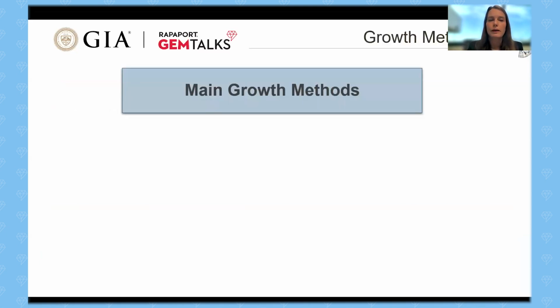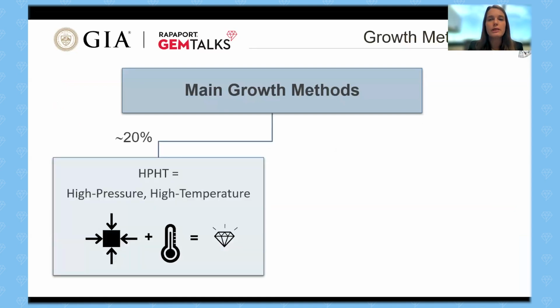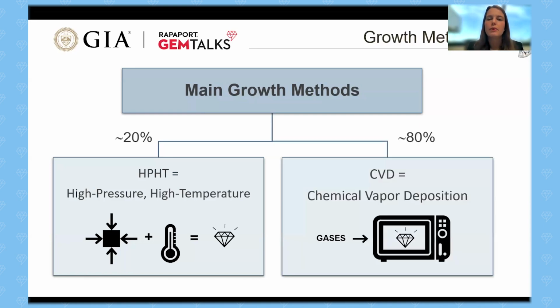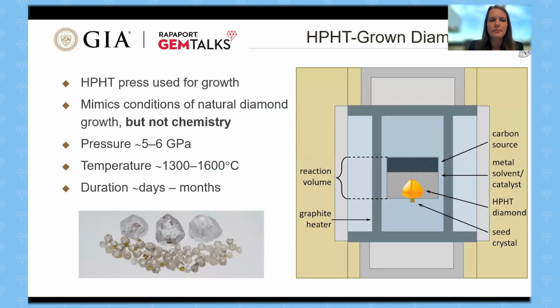Now, moving on to the growth methods. For the main laboratory-grown diamond methods, about 20% of what we see at GIA is produced by the high-pressure, high-temperature method, where you're effectively compressing and converting a source of carbon at very high temperatures and pressures, trying to mimic some of the natural diamond formation methods. And then the remaining 80% is produced by the chemical vapor deposition method. And this is dramatically different. It's based on gas phase chemistry. And I like to think of it as a very fancy microwave oven that's able to grow diamonds. But we'll look into these two methods in more detail now.